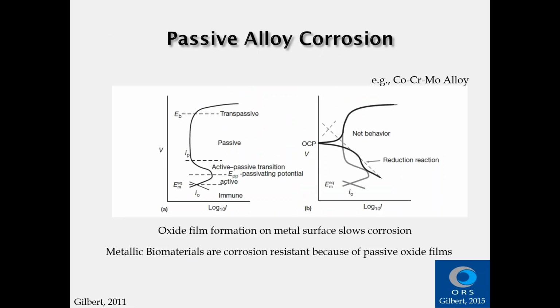in corrosion. When you have a passive alloy present, the oxide film shows up at certain voltages, not at all voltages, but at certain voltages, and will passivate that surface and reduce that active corrosion. So in that prior picture, the active curve might have been this line continuing out, but at this passivating potential, oxide film begins to form and covers that surface and makes the currents much less than they would be in the absence of it. In some alloys, like stainless steel and cobalt chromium, there's another potential, the breakdown or transpassive potential, depending on the alloy, where you begin to get a runaway, essentially a loss of the passivity of the oxide film, and either pitting corrosion or a generalized corrosion attack of that surface. When you superimpose the reduction reactions on that curve, this black line is the representation of what you would measure in a simple polarization test.